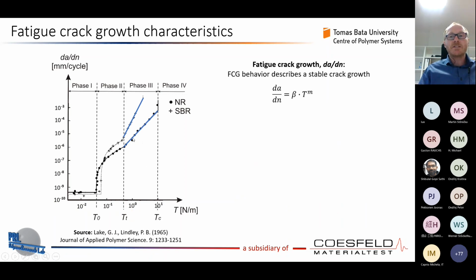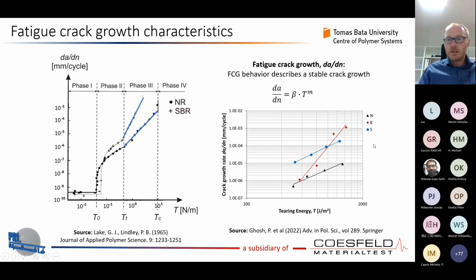Then we have phase 3, which is stable crack growth described with a power law. And again, some data or diagram investigation of three different materials, again from Dr. Ghosh, from the second book, where Dr. Ghosh nicely presented a lot of influences on the fatigue crack growth characteristic. These are results for pure natural rubber, styrene butadiene rubber, and butadiene rubber. As you can see, that nicely corresponds with what Chris presented in the first presentation. We have the largest resistance against fatigue crack growth in natural rubber, the weakest material is butadiene rubber, and in between is styrene butadiene rubber.